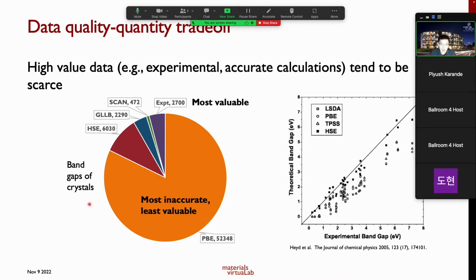One of the classic examples is the band gap, right? Today we can do DFT calculations using the PBE functional, and we can already get about 50,000 band gap data points. So this is a very good and large data set. However, the PBE functional is also one of the most inaccurate and least valuable in terms of band gap accuracy. We all know that the PBE functional tends to systematically underestimate the band gap.